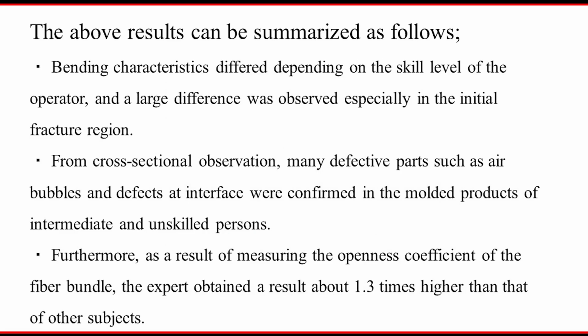And then bending characteristics differ depending on the skill level of the operator, and a large difference was observed, especially in the initial fracture region, initial fracture stress. From cross-sectional observation, many defective parts, such as air bubbles and defects of the interface, were confirmed in the molded product of the intermediate unskilled person. So the interface part has a void in the case of the intermediate unskilled person.